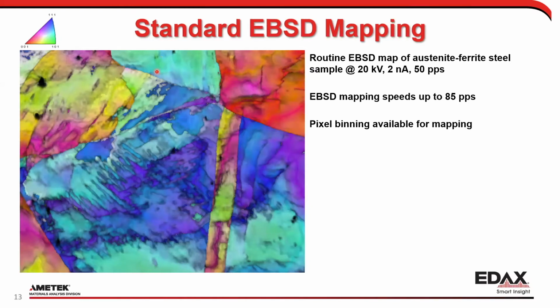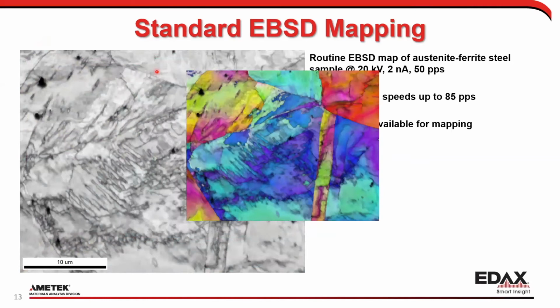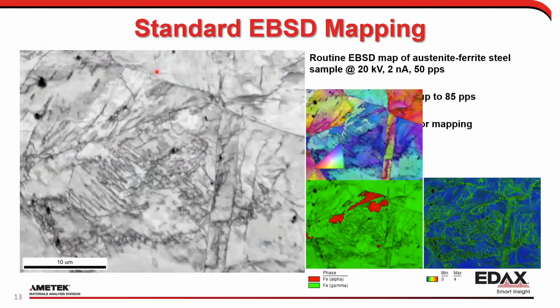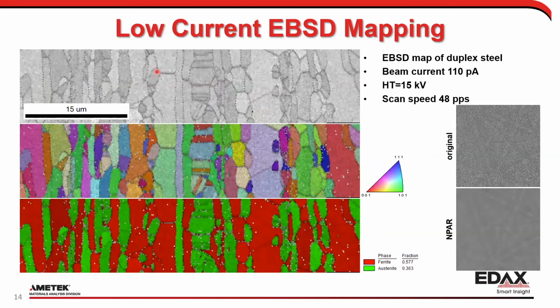So again, you look at this, you can see that it does a good job with the phase differentiation, and also looking at fine scale deformation features. Again, we can see that over there on the CAM map. It also works at low current. This is honestly underselling the camera by quite a bit on this sample here.